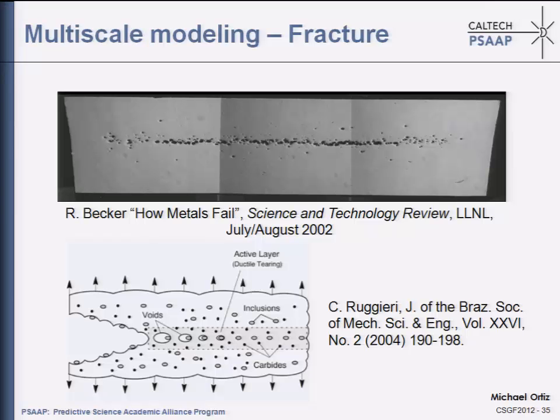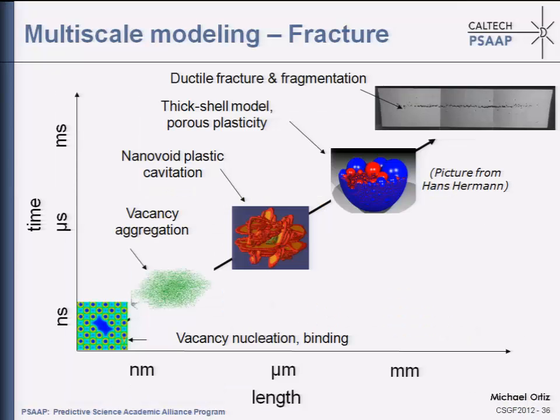And here, the multiscale hierarchy that you find is that the ductile fracture of the material is ultimately the net effect of the formation of voids and the coalescence of voids. So if you look at it again as a multiscale problem, here at the top level, you have the formation of a ductile crack that causes the failure of the material. If you start looking down, you see individual voids that grow under the action, for instance, of hydrostatic pressure. Then these voids somehow nucleate at some point at the nanoscale by emission of dislocations. So that would be the nucleation event. Perhaps the nucleation sites are second phase particles, for instance, in steels, or something that is pre-existing, or under extreme conditions, the nucleation sites can maybe be generated by vacancy aggregation.